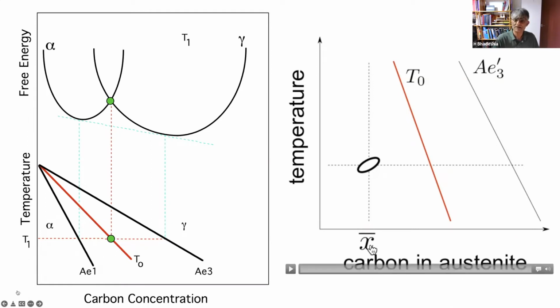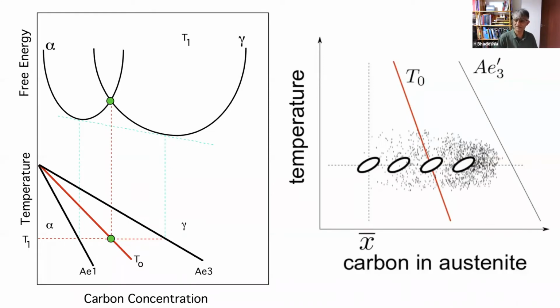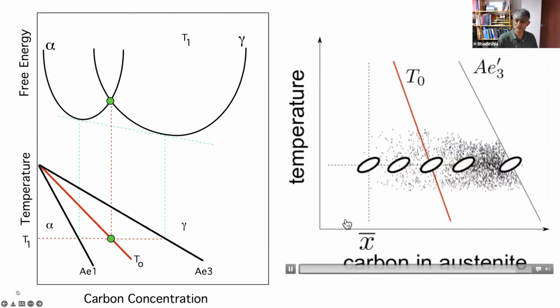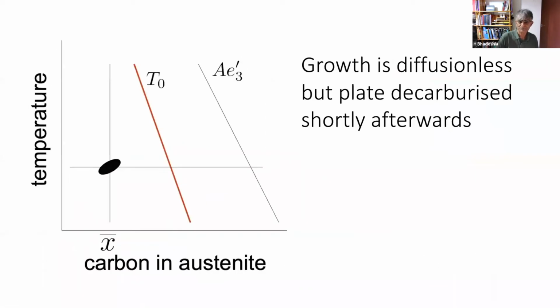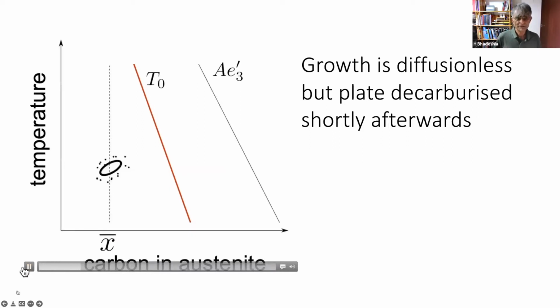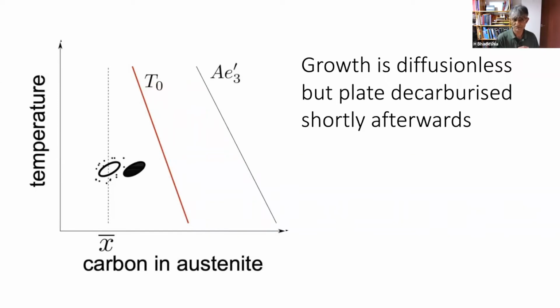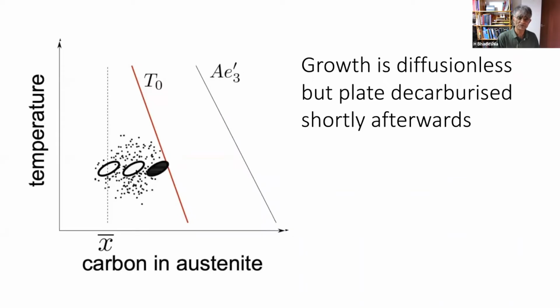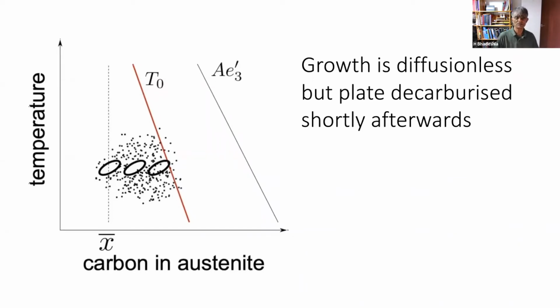So let's imagine that we form a plate of bainite, but it partitions carbon as it grows. Okay, in other words, it never has excess carbon. In that case, this is the average carbon concentration of my steel. In that case, the reaction will stop when the composition of the austenite reaches this phase boundary. Alternatively, if it forms like martensite, but after the growth event, it partitions carbon, then the reaction cannot proceed beyond the T0 curve. Okay, so that defines the thermodynamic limit for that mechanism of transformation. You cannot have diffusionless transformation beyond T0. Okay, so this would form a really clear indicator of whether the transformation happens with the partitioning of carbon, with the ferrite never having an excess of carbon, or subsequent to transformation.